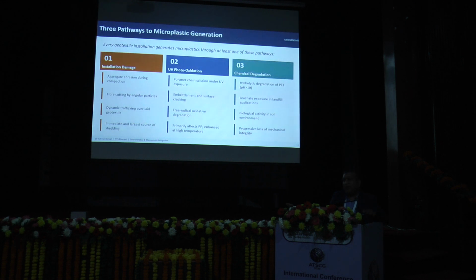Whenever a geotextile material is laid down on the road and we go for compaction of the dirt and stone particles, a force is applied. Due to that, there is leaching of microplastic from the geotextile materials, or maybe fiber cutting by some abrasive material applied during road construction. Then dynamic trafficking over the laid geotextile: whenever the road is completed, due to the traffic load microplastic is also released. The immediate and largest source of shedding is the installation. Whenever we initiate the laydown of the geotextile materials, microplastic release starts, and this is the biggest source of microplastic generation.